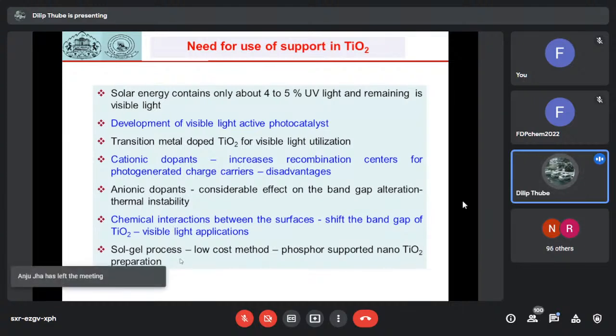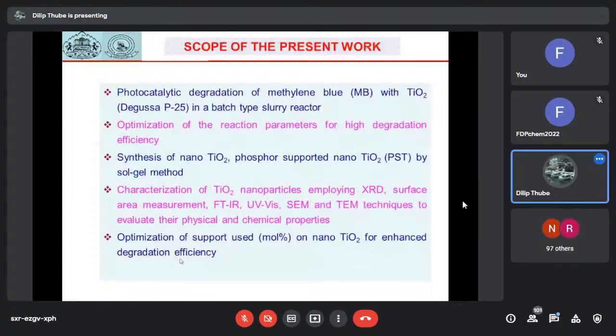And therefore, transition metal doped TiO2 can be used for visible light photocatalysis. And these transition metal dopants could be cationic dopants, anionic dopants, or certain oxides which can be used as a support, which can be prepared by using a very low cost, inexpensive method, that is the sol gel process. And in our method, we are going to use phosphor materials as a support for the preparation of a supported TiO2 nano photocatalyst. So the scope of the present work is the photocatalytic degradation of methylene blue with TiO2 in a batch type of slurry reactor.